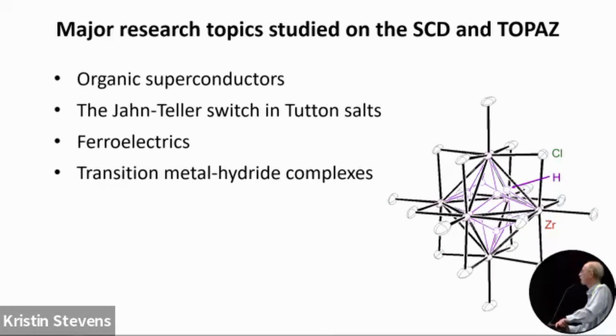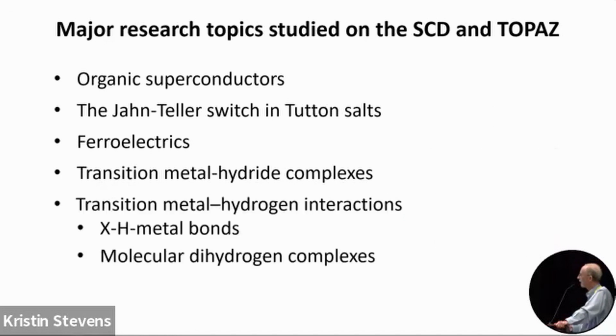We've done a number of transition metal hydride complexes. This is one from Al Cotton's group. It's a zirconium cluster, well, 6 zirconium atoms and hydrogen atoms sitting on the face of the octahedron here. And the results agreed very well with calculations in this case. And finally, I'll talk about some transition metal hydrogen interactions involving XH metal bonds and molecular dihydrogen complexes.